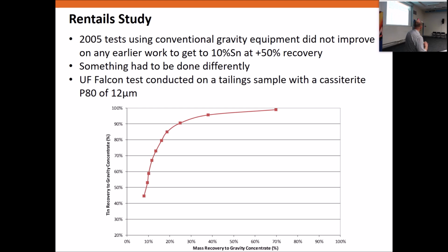And happily at that time, an opportunity to try an ultrafine Falcon lab unit came up. So the first test was literally go down the back with a scoop and grab a sample of some slime tailings, which had a cassiterite 80% passing size of just 12 microns. And we got an amazing result. You know, we got roughly 90% tin recovery into just 25% of the mass.